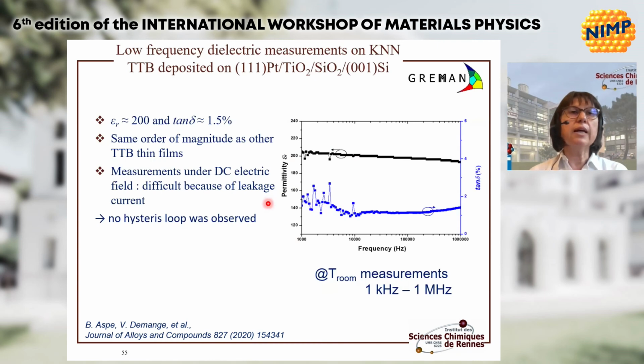From these results, dielectric measurements have been performed. At low frequency, we can see a dielectric permittivity of 200 that is more or less stable in this range of frequency, with tangent delta of 1.5%. This is the same order of magnitude as other TTB films. I remind you that this is the first time that these TTB KNN films have been characterized from an electrical point of view. So it's comparable to other TTB systems.